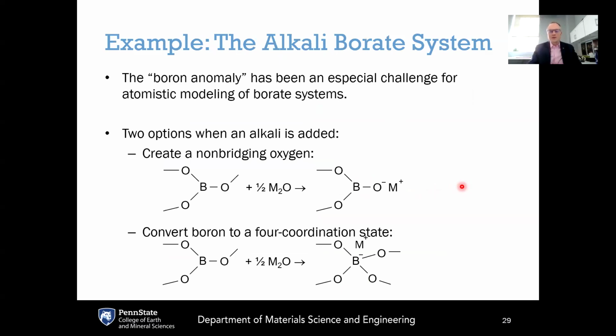Let's take a simple example to see how this works. Consider the alkali borate system. And borate systems are interesting because of this so-called boron anomaly. Boron can exist in threefold coordination or in fourfold coordination. And when you add an alkali modifier to a borate glass, it can take on two different structural roles. It could convert the boron from a threefold coordination to a fourfold coordination, as shown here. When that happens, the connectivity of the network increases. It increases the glass transition temperature, and so on.